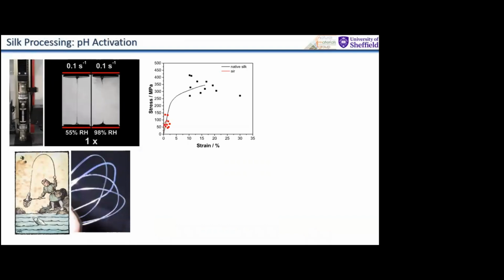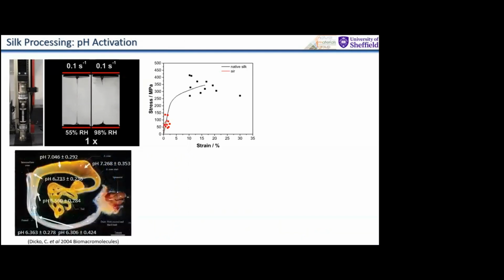If you take some learnings from fly fishermen, who originally, before the nylons were invented, used silk guts. These were silkworm glands that were dipped in vinegar and then pulled through the teeth in order to make fibers for their fly fishing lines. The trick there is not just the pulling through the teeth, it is the exposure to acid, to vinegar. Because if we look inside the animal, what's been found by collaborators is that there is a steady decrease in pH and increasing acidity as silk moves down this duct.